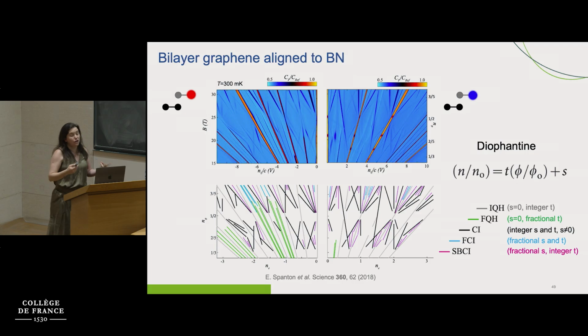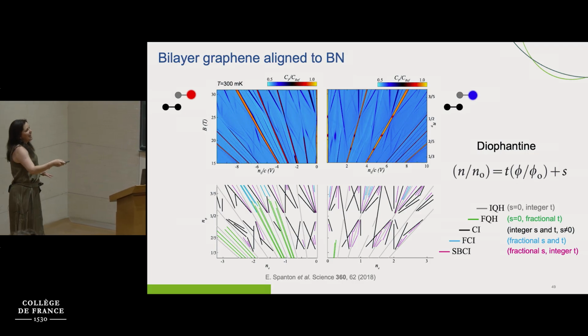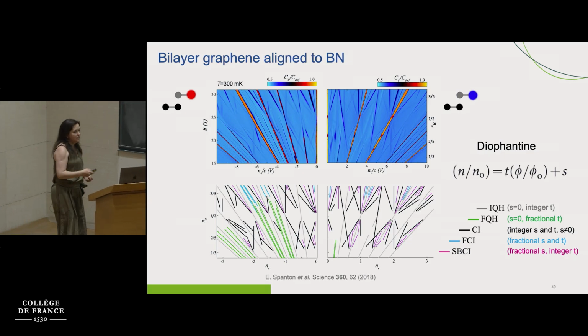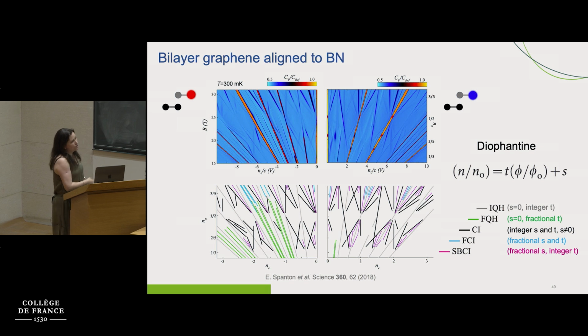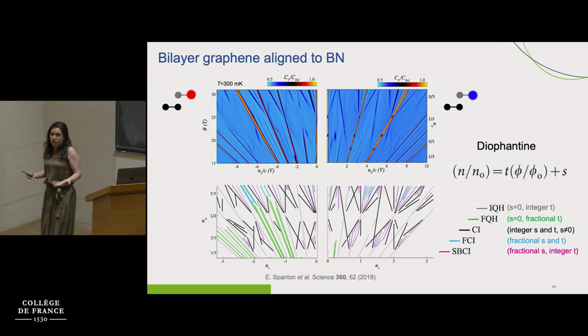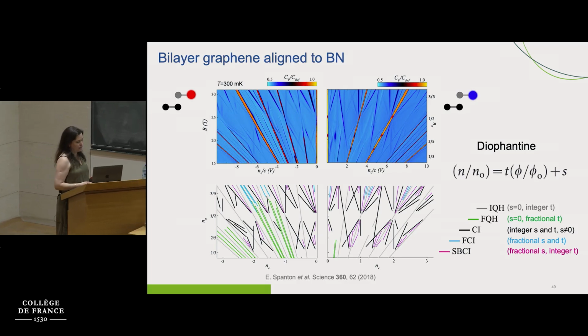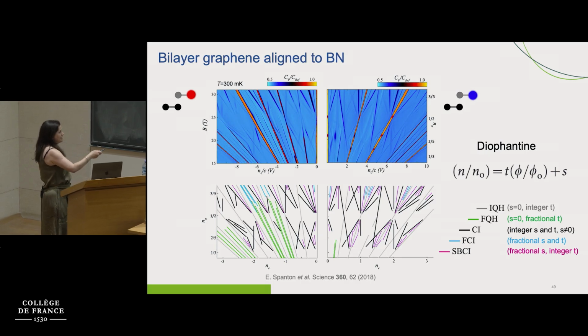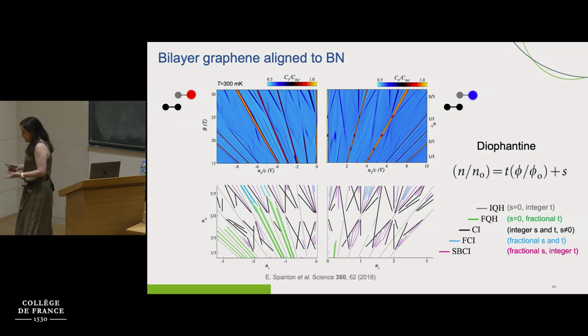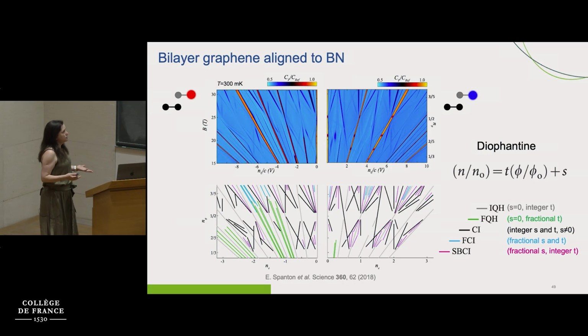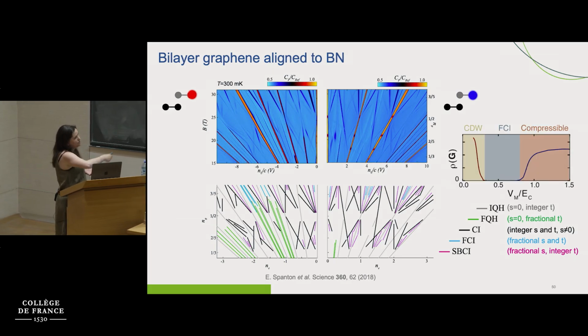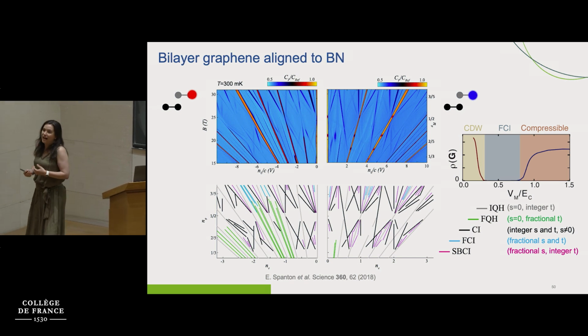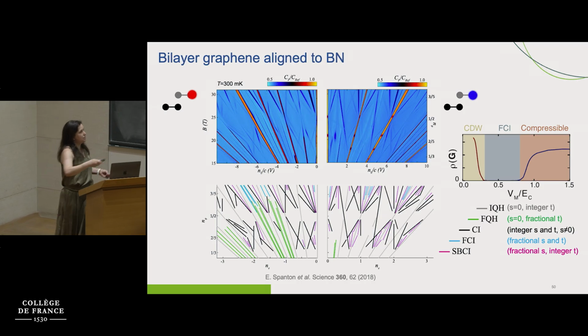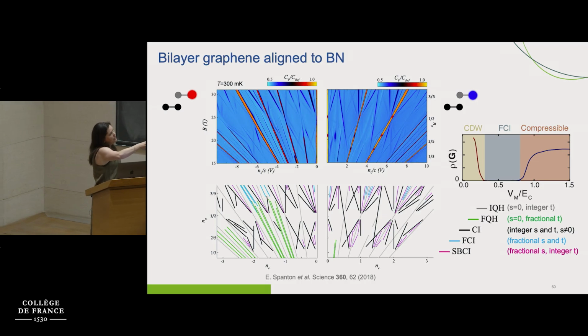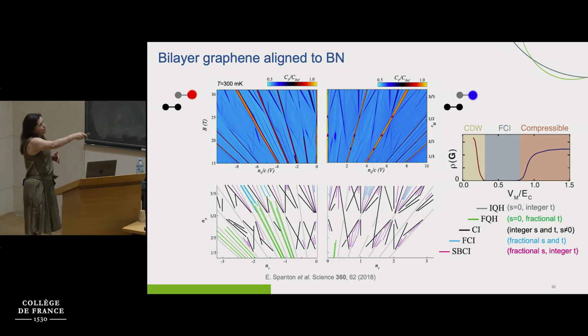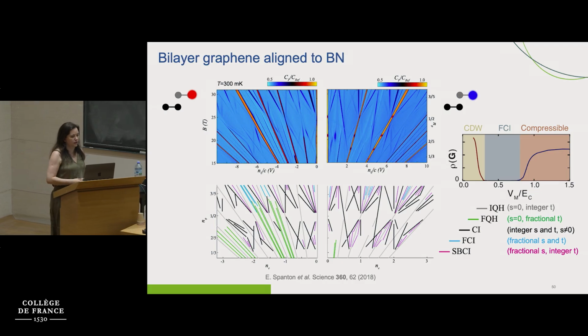You're going to also have two things that are new and very exciting, which are fractional s and t, which is a fractional Chern insulator. We're going to see it just in a second. And we're going to have symmetry broken Chern insulators. Both of them are the result of interactions, and they are very active subjects of research currently. Okay, so why can we see this here and not in a regular bilayer graphene on BN but not aligned? The reason for this is that you need a certain number of interactions, but also you need to compete, in this case, with the lattice potential. And in fact, this fractional Chern insulator can be stabilized only in a range of this ratio. After that, what you get is a compressible state, which is just an electron solid state.